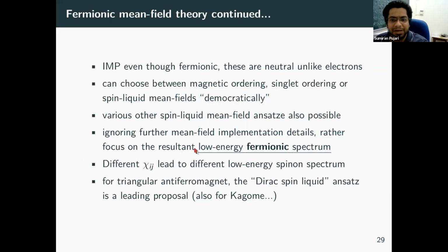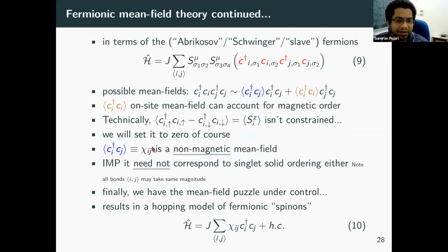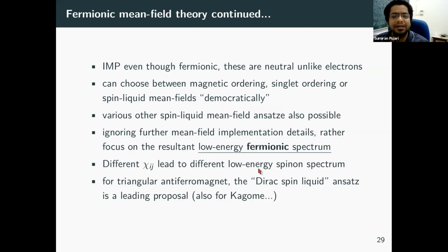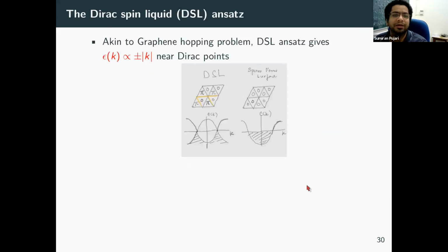But I'll ignore those implementation details, and rather focus on the resultant low energy fermionic spectrum, with different kinds of mean field guesses on these matrix elements. This kind of mean field and the resultant hopping model leads to different low energy spinon spectra. For the triangular antiferromagnet, there's this thing called the Dirac spin liquid ansatz, which is going to be relevant to this material. So this is like the graphene hopping problem. And this DSL, or Dirac spin liquid ansatz, actually gives us a mod k, linearly dispersing fermionic spinons instead of magnons. So there are some cartoons.